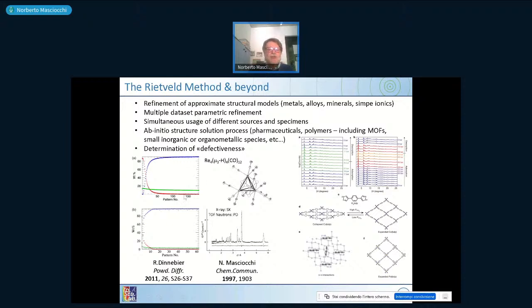Here there is a parametric refinement. By parametric, it means something which changes slowly. Here it's a paper in which the material was heated, so the pattern number goes with the temperature. You can see that the percentage of one material versus the other decreases, one increases, and the percentage of the green one is kept constant. It means you can study kinetics and transformation in the solid by using a heating stage and a single refinement where among the parameters you put the shape of this curve, and automatically you will get the position of these flexes, the height of this curve, and so on, because you use multiple data sets at the same time.